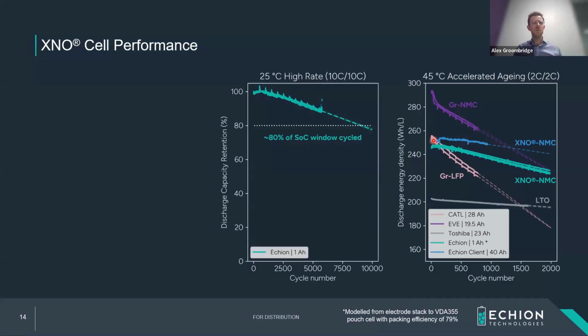When we look for very high C-rate operations, if you think about a hybrid application, you want to have high input, high output, continuous, and it's being used all the time. Obviously, you look more at drive cycles, and you'd have quite different results there in a proper mining operation. A simple test is just doing symmetric 10C cycling. So 6-minute charge, 6-minute discharge. We cycle 80% of the SoC window by doing this, and you can see we're roughly out to 10,000 cycles in our cell design that we have here.